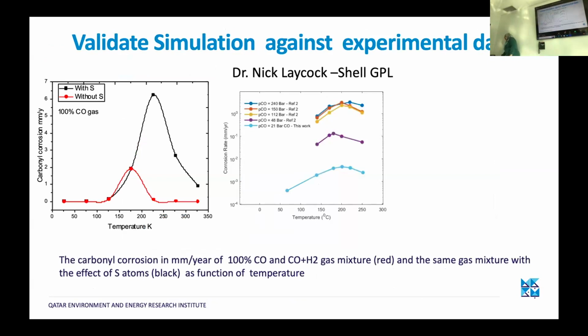And this actually implies that if we look at the carbonyl corrosion in millimeters per year, and we try to compare it to the experiment, we see that our corrosion rate is orders of magnitude higher. Here we're talking about 1.5 millimeters per year, versus 10 to the minus 3 millimeters. So there is a disparity, but in terms of behavior, this is the same behavior that we see from the Shell GPL. And you can see that in this case, sulfur is enhancing the carbonyl corrosion.